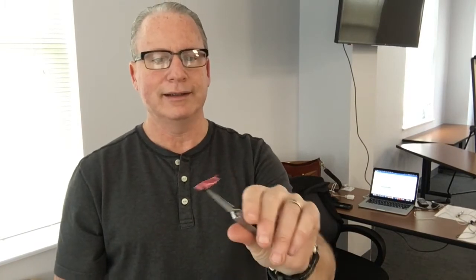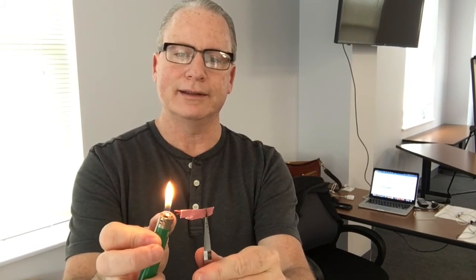Here's our last one we'll look at. It looks like polyester — maybe it is, maybe it isn't. Bring the flame in. It doesn't pull away, so it's not a plastic. It's a natural fiber. Let's go ahead and burn it. This one has a sputter to it, a little bit of smoke. It goes out on its own and it smells really bad. That is silk. Looking at the fabric itself, you probably couldn't tell what it was — of course, that's a small sample. But when you do your fiber ID testing, you can tell what the problem fibers are.